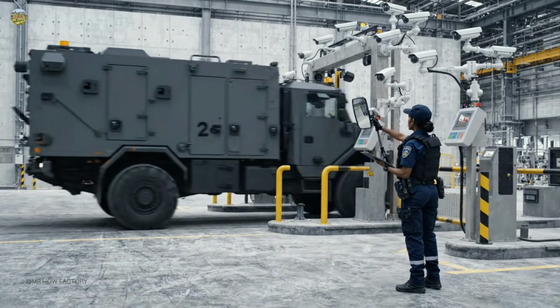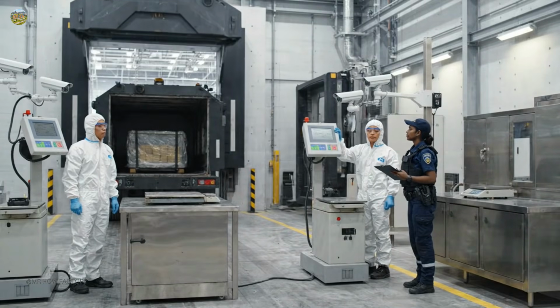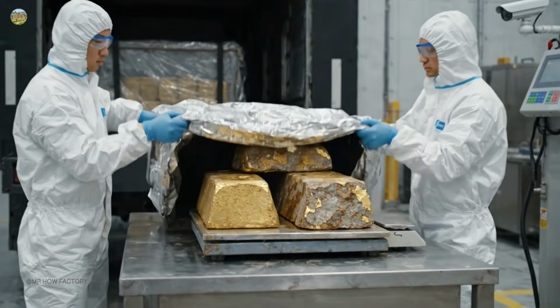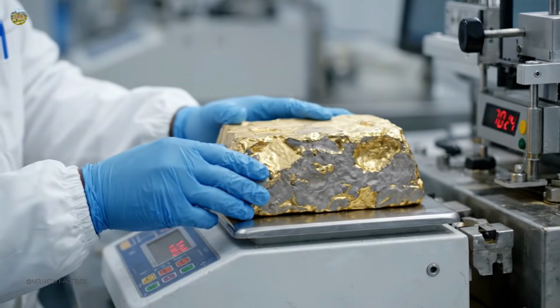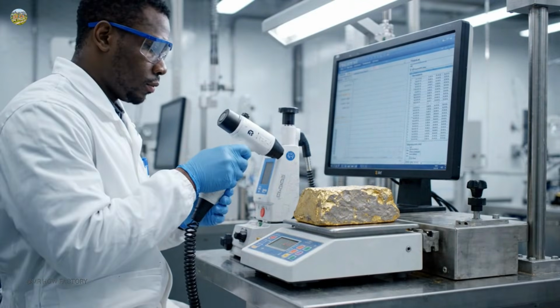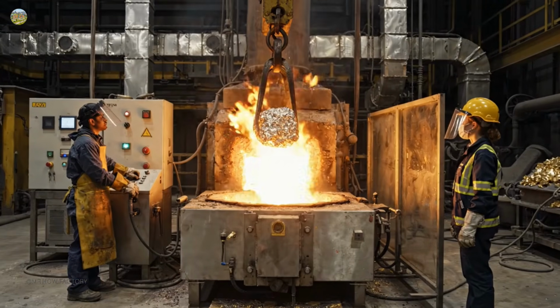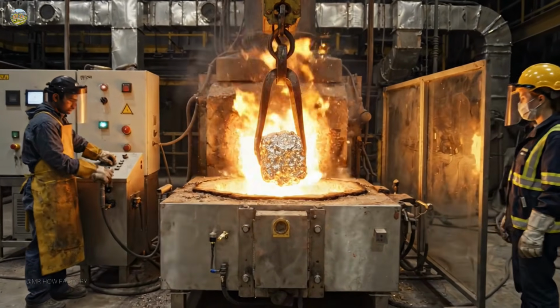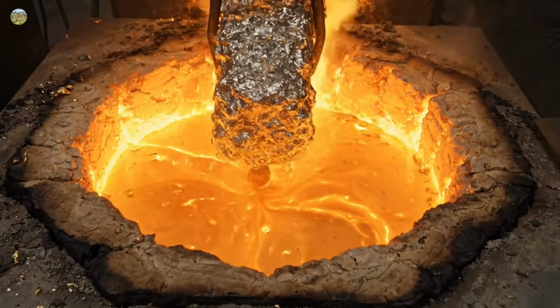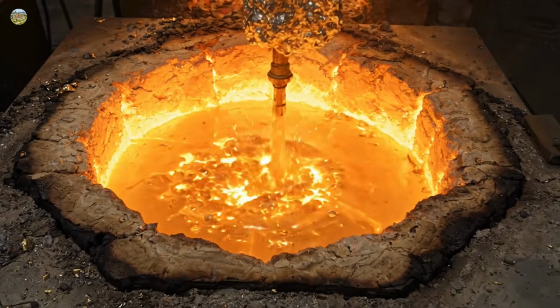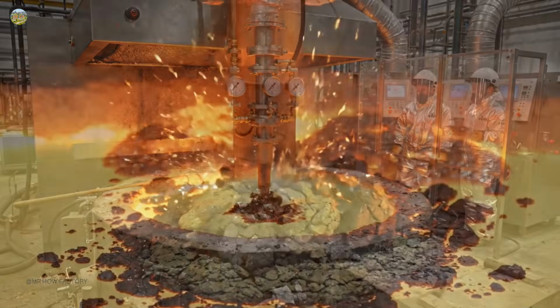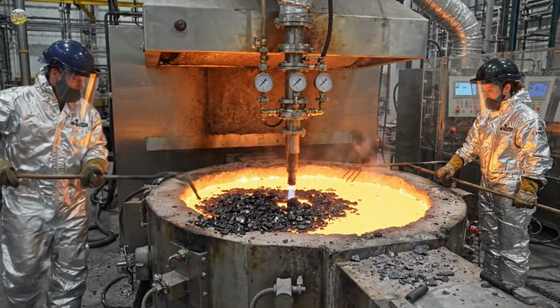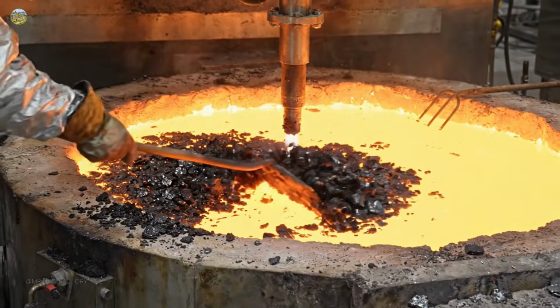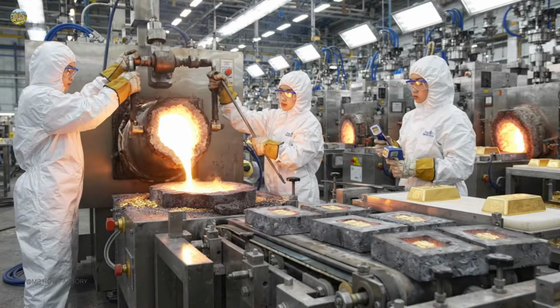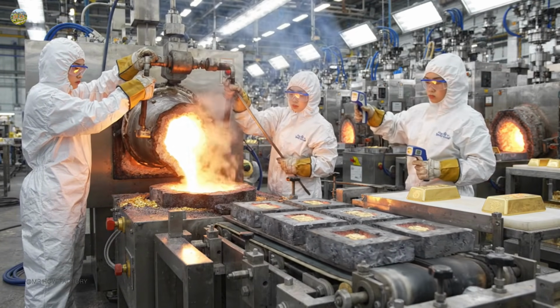Doré bars are shipped under heavy security to high-tech precious metal refineries. The first step is the Miller process. The doré bar is melted down inside a furnace. Chlorine gas is blown directly into the liquid gold. Impurities like silver and copper react with the gas and float to the top as solid waste. Gold does not react with chlorine, so it remains behind at 99.5% purity.